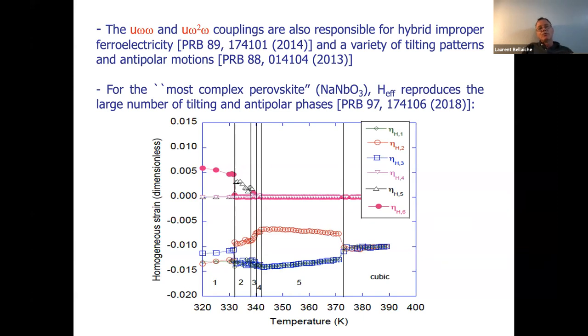And they're also responsible for a variety of tilting patterns, not only this simple A minus A minus C plus, but let's say along the C axis, instead of having plus minus or plus plus, you can have a combination between these two. This means on a phonon spectra, you can go from the R point to the M point in between these two. For example, in sodium niobate, there are 7 phase transition sequences, and we are able to reproduce all of them in this recent paper of 3 years ago. And each of these has different tilting patterns. Some of them, for instance, need 12 lattice constants along the C axis to reproduce the patterns. And you can do that these days with effective Hamiltonian.